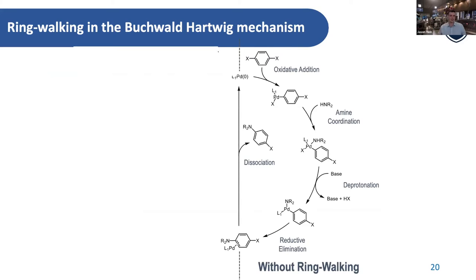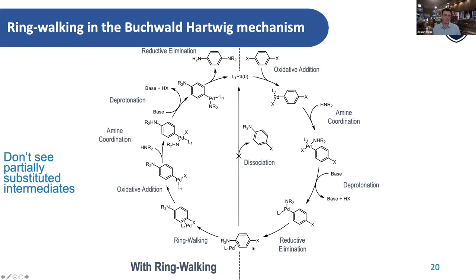That's one coupling event. But what's interesting is that we get a process known as ring walking. If you notice, this coordinated event here, this palladium coordinated on as the product, looks a lot like what would be the first intercept complex between palladium and your halide. So if you have a molecule with a contiguous pi system and another halogen on the other side, you can get what's called ring walking, where this dissociation event is capped off. The palladium simply slides across the ring to do a new oxidative addition event and then subsequently repeats the cycle.